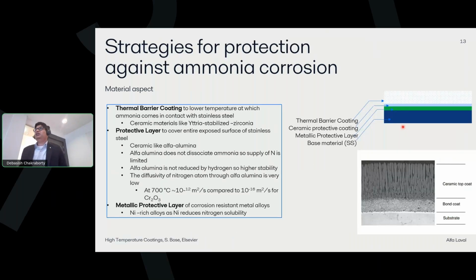Okay, then what are the strategies? There is no way to avoid corrosion, so you need to come up with some strategy. This is something that we try to follow: a thermal barrier coating. This could be a ceramic, like YSZ, yttria-stabilized zirconia, and this could lower the temperature. The lower the temperature, the less dissociation of ammonia, and in that way it reduces the nitrogen atom concentration on the surface.